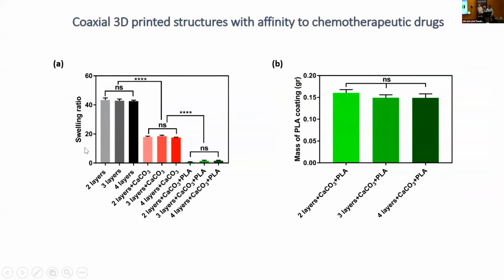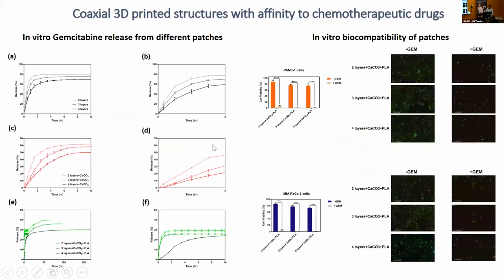So we've also done the swelling ratio studies to see how these modifications affected these patches. After the final adjustment with calcium carbonate and PLA coating, we have significantly reduced swelling ratio, which is normally associated with burst release of the drugs. We've done the in vitro release studies on gemcitabine, and the samples that had both calcium carbonate and PLA showed a prolonged release of drugs up to 7 days.